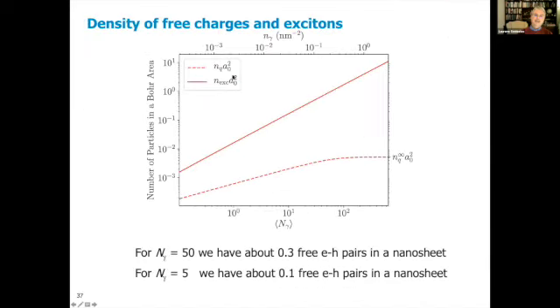Now, if you look at the density of free charges and excitons as a function of the number of absorbed photons in a nanosheet, you see that you have a very small number of free charges in a Bohr area, much smaller than the number of excitons. And if you calculate back, then for 50 photoexcitations in a nanosheet, we on average have 0.3 free electron-hole pairs per nanosheet. So every 3 nanosheets, there's a free electron-hole pair. And if you have 5 photons in a nanosheet, it's about 1 in 10 free electron-hole pairs in a nanosheet.